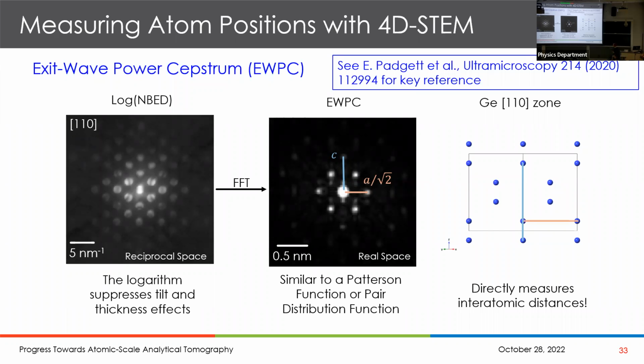And I'll explain that very briefly, which is that you get that nano-diffraction pattern. If you take its log, it actually makes it a lot less sensitive. It suppresses things like tilt and thickness effects in the result. And if you take the fast Fourier transform of the log of a diffraction pattern, you get back to real space. But you get basically a very high quality representation of where the atoms are about some central point. And this can be used to very precisely locate the atoms in the specimen.